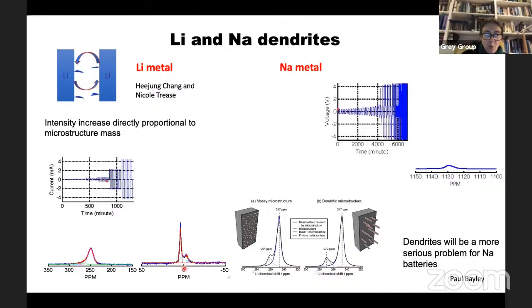At the same time, watch the signal at 0 ppm. This is the signal due to the electrolyte that's decomposing to form these SEI compositions. So you're watching the growth of a dendrite and at the same time the formation of this passivating layer over it. And this movie here is just to show you that dendrites are an even bigger problem for sodium.